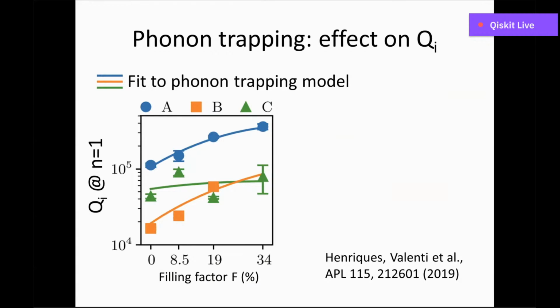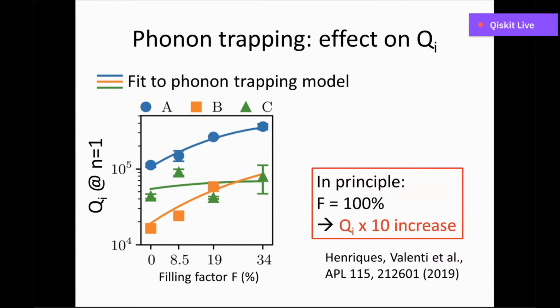quasiparticles generated by phonons. Again, we can fit this data to our model and extrapolate what would happen for a full or almost full phonon trap coverage. And these would yield a tenfold increase in internal quality factor at single photon drive.